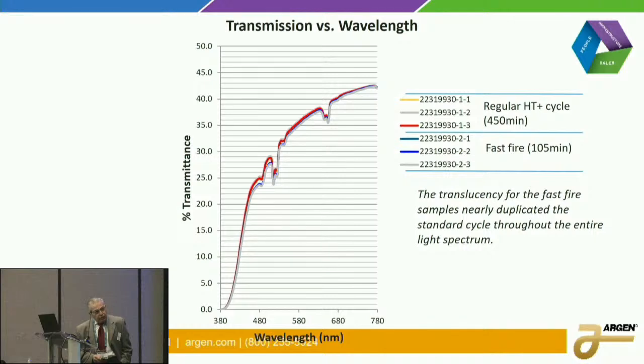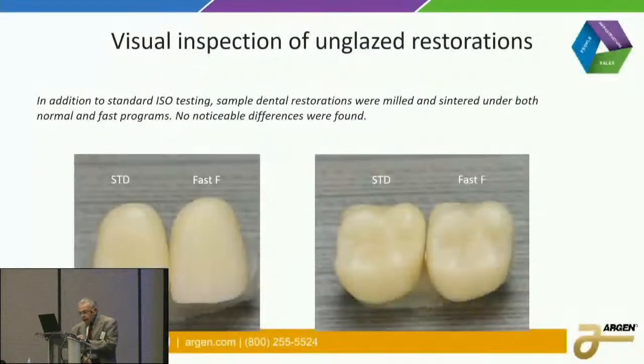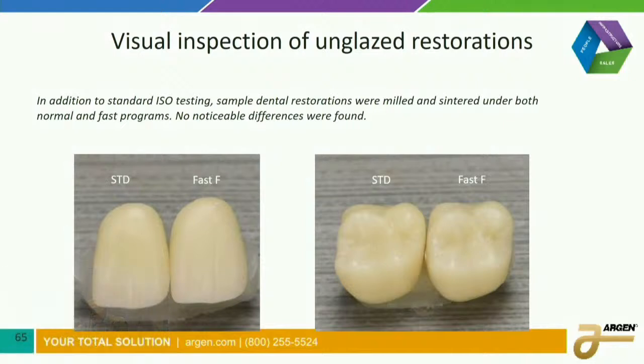And here's the full transmission, the regular cycle and the fast fire, and you see they trace very, very well. These little dips are where the coloring material is absorbing the light and reflecting it. So here you have a manganese gray, cobalt blue, and the iron yellow. Okay. So when you look at the units themselves, they look fairly good, and they're fairly consistent.